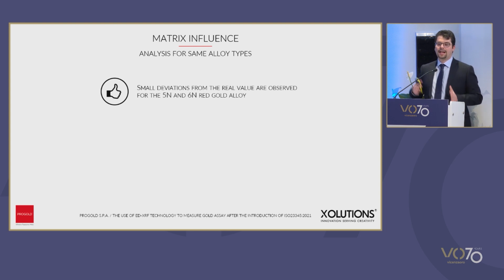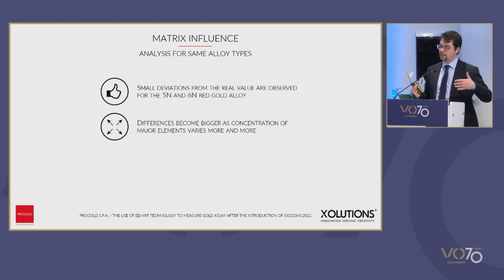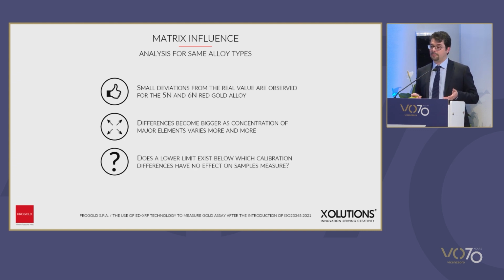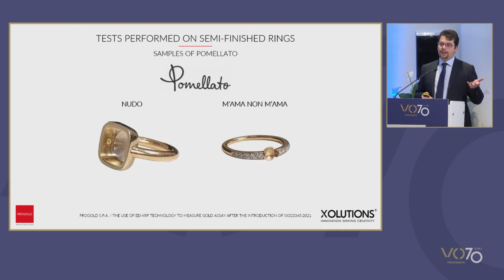That for small deviations from the real value, we have results which are in line with the previous ones, while as compositions differ, our results will worsen gradually. We still have to establish whether there is a lower limit which requires a more systematic test. That is, what can be the difference between the compositions used, in order not to excessively affect the results.